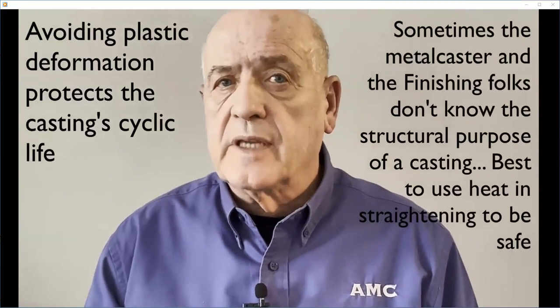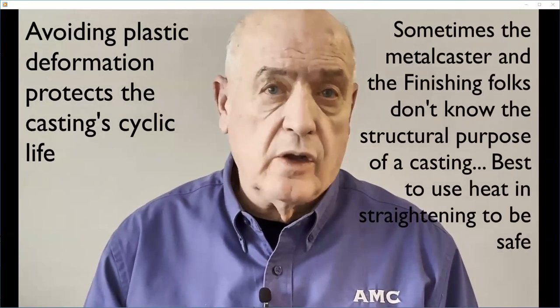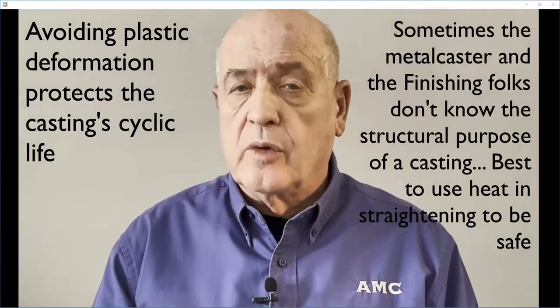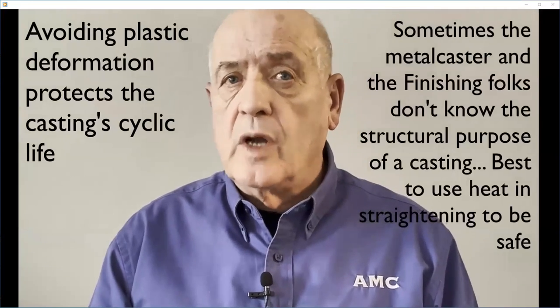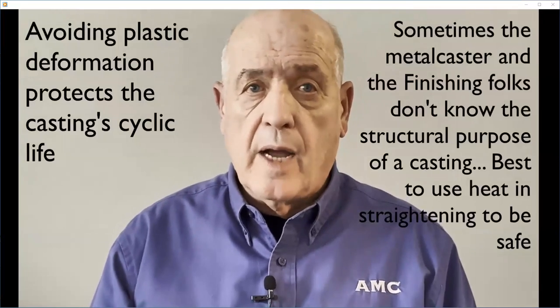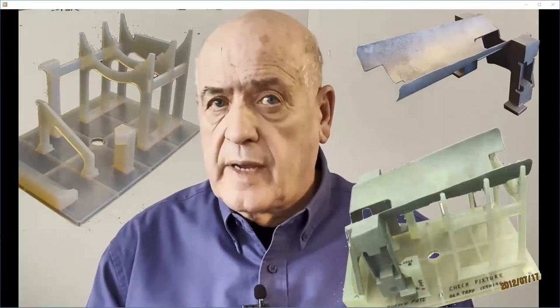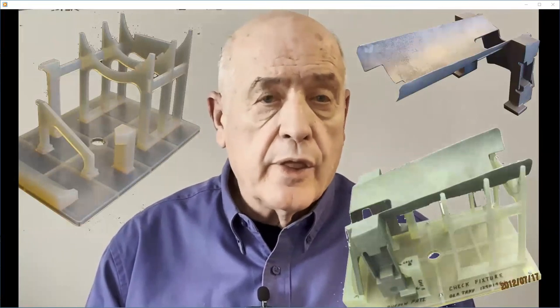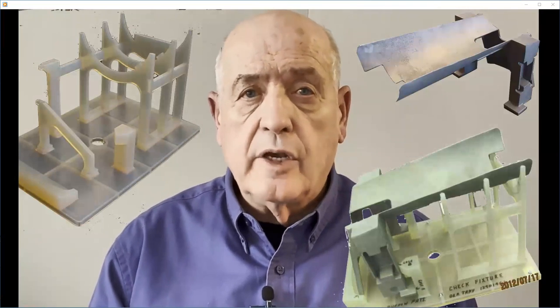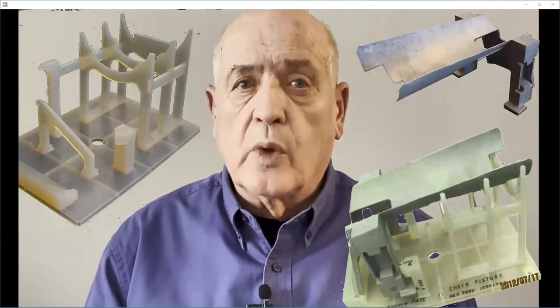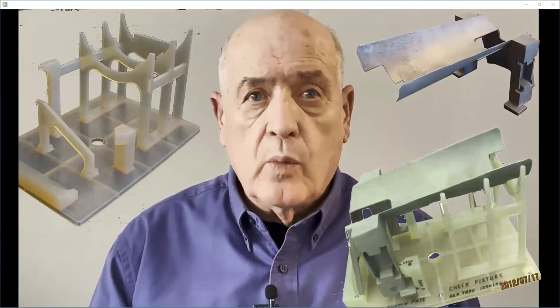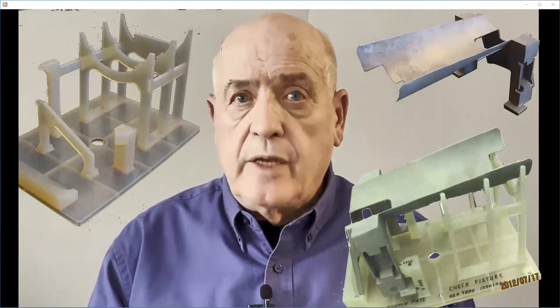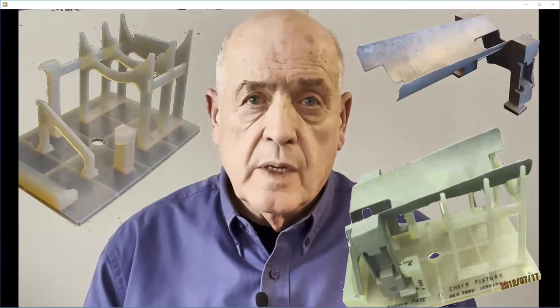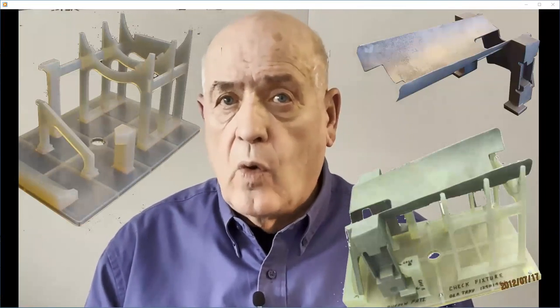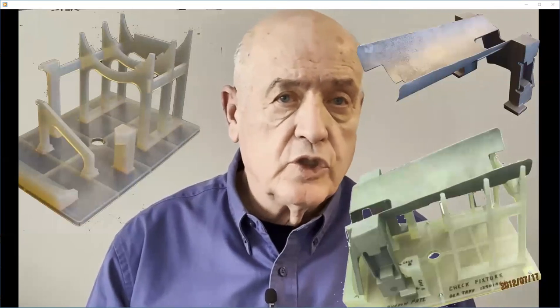It's proper practice to heat the casting to an appropriate temperature depending on the alloy to prevent plastic deformation while straightening. That way the casting's structural life, if that's important, won't be compromised. Here we see a high specification, very complex, high alloy steel casting being checked for straightness in a quick 3D printed, durable nylon dimensional checking fixture. Usually castings are straightened by a skilled operator with a press, a torch, and manual straightening blocks of various shapes. The checking fixture is used over and over to verify the progress of the straightening increments.